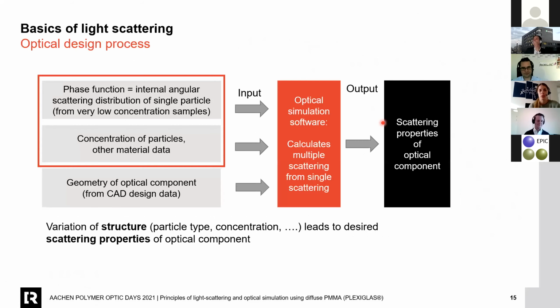Now I go over to our optical simulation topics. Before I explain how we get the parameters for the simulation model, I give you a short introduction into the simulation process. You need a few input parameters. At first, the phase function of a single scattering particle. It's the internal angular scattering distribution of the single particle. Then you need the concentration of particles, so you can use the mean free path value, and other data such as the refractive index or the absorption coefficient. This data is what you can get out of our production information.